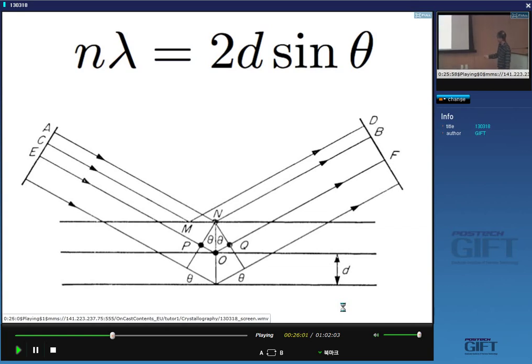And if that path difference here, which is 2d times sine theta, d is the distance between the planes, and this is the angle theta, and this is also the angle theta, PO plus OQ is 2d sine theta. If that's an integral number of wavelengths, n is an integer, and lambda is a wavelength, if the path difference is an integral number of wavelengths, then these two will reinforce and you get diffraction. But if it's not, then you will get destructive interference. If it's half a wavelength out of phase, you'll get destructive interference, right?